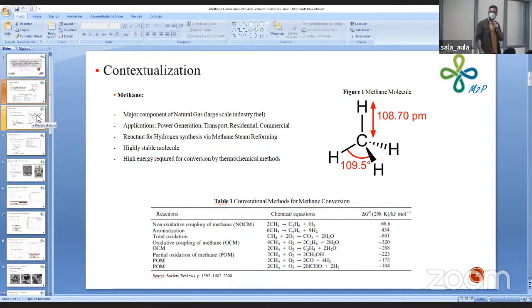But coke formation is favored here, and it leads to deactivation of the catalysts that are needed for these reactions to occur. We have the oxidative processes, like the partial oxidation of methane and the oxidative coupling of methane. But in those reactions, total oxidation is thermodynamically favored, as we can see by its Gibbs energy. So these processes are hard to control, and we have low yields and selectivities.